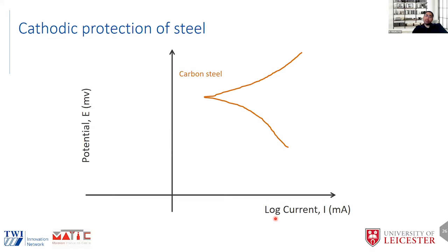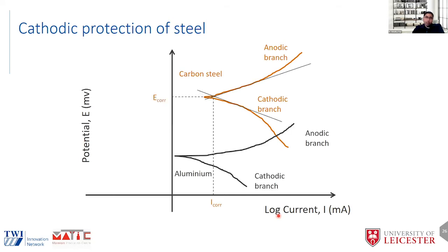So I'm presenting a schematic of a classical diagram, which people use quite a lot. Here we have the anodic and cathodic branches of carbon steel. Similarly, we'll have the same for aluminium. So you can work out the cell corrosion rate of carbon steel and the i-corr value for those. Similarly for aluminium. And when you bring them in galvanic contact, you get a mixed potential. And by extrapolating the anodic branch of carbon steel here, you can find out the reduced corrosion rate of carbon steel. And you also get the enhanced corrosion rate of aluminium that might happen.